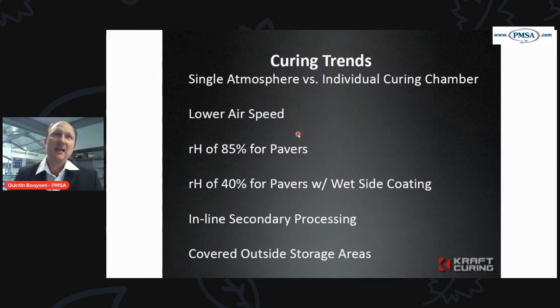Lower air speeds are critical, because you don't want to dry products out. As we said earlier, we want them to cure, not dry. Another thing is relative humidity of 85 for pavers. It has been found that this also helps to reduce the efflorescence, and it helps to just get a better product quicker when you're doing paving.